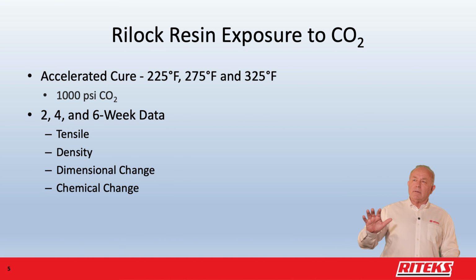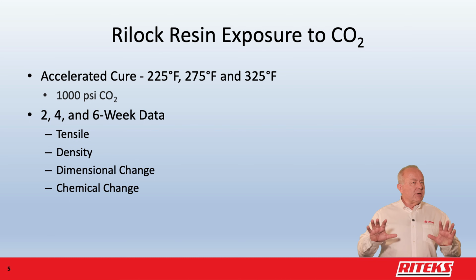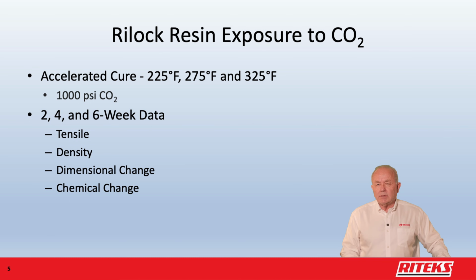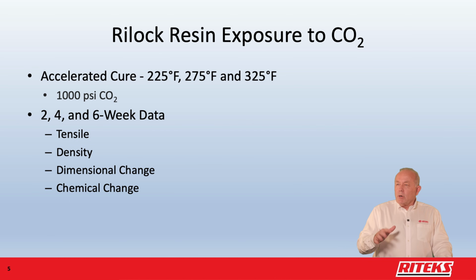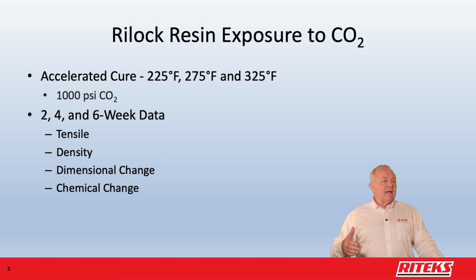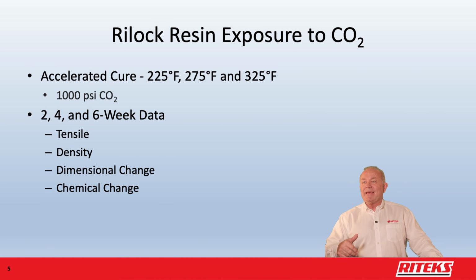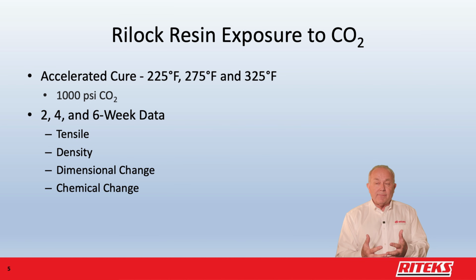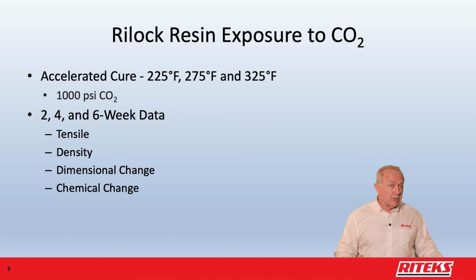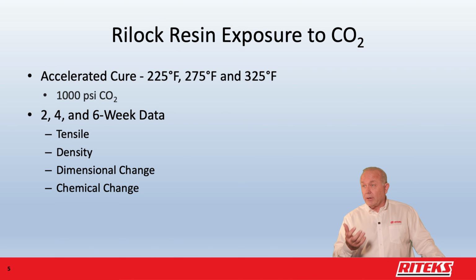Much higher temperatures than normal for CO2 resistant materials. We submerged these in aqueous fluid at 1,000 psi CO2 pressure. We did up to 6 weeks data looking at things like tensile strength, density, dimensional change, and really even chemical change. And I'll discuss that a little bit later on how we did that.